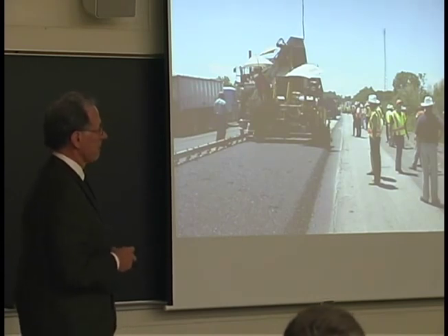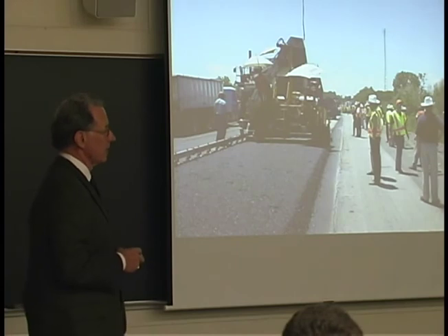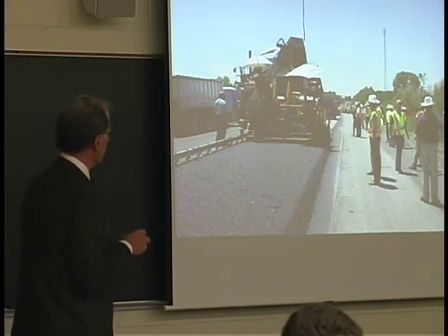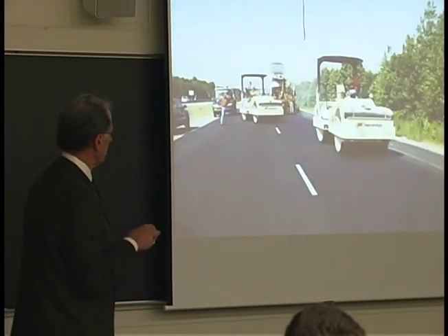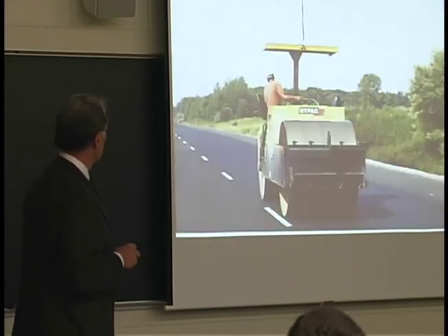Now, coming from Mattoon to us, you drove east on Lincoln, and you have this bump. Why is that? Because that was originally a concrete pavement, and that's the cracks in the concrete pavement. That was one thing that they wanted to eliminate on I-70, so we went in and we crushed up all the concrete pavement. Again, we'll see some pictures. We made it back to stone so that there wouldn't be any bumps. This is the rollers that we had on Interstate 70. Again, more equipment, more rolling.